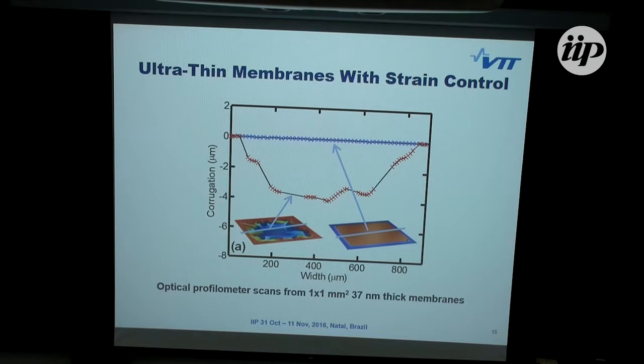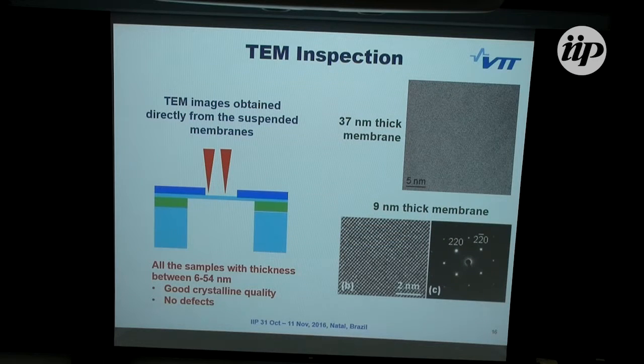This is an optical profilometer image or scan of this, so we can really make this flat. Without this, the corrugation is of the order of several microns. And the quality after release is still very good. There are TEM images obtained from the suspended membranes, from the central and edge part. This is a 37 nanometer thick membrane.